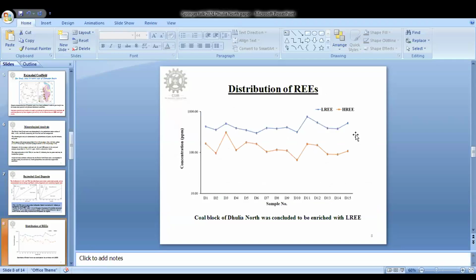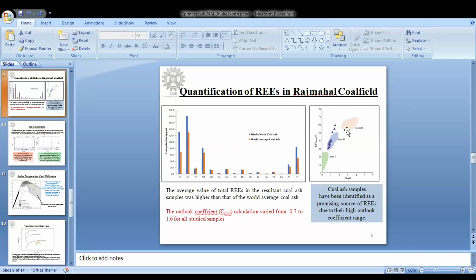Now coming to the rare earth distribution, what we found was that the coal block of Dhulia North was enriched with light rare earth elements. Heavy rare earth elements are usually very much in lower quantity in the Indian subcontinent. We have done distribution studies for several other areas, and we found that has been the consistent observation. And even for Dhulia North, it was the same, that it is enriched in lighter rare earth elements.